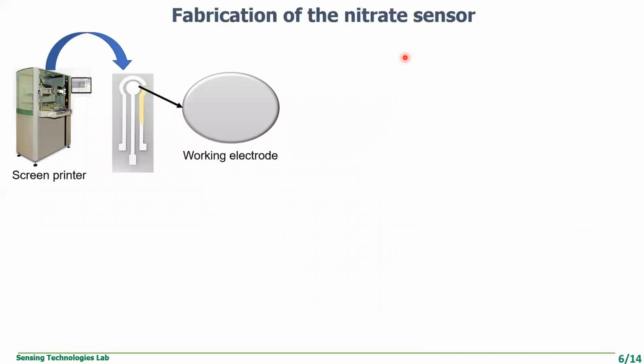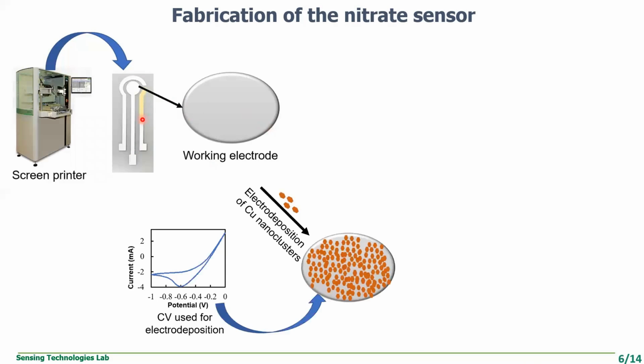Then the fabrication of the nitrate sensor. Here I will demonstrate the fabrication step by step. So at first, a semi-automatic screen printer is used to screen print the sensor with the silver ink, and half of the reference electrode is screen printed with the silver chloride ink. Then we can go directly with the copper electrodeposition on top of the working electrode using cyclic voltammetry. This is called the copper silver sensor.